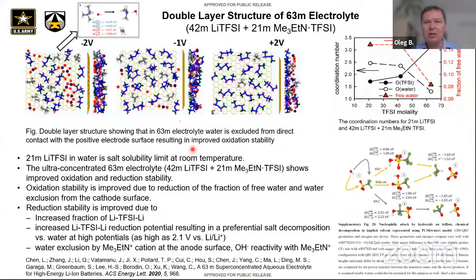One of the ways, Chunsheng Wang's group again came with a new mechanism. They said that, well, we can increase salt concentration further, decrease the amount of water overall, and increase solubility. After they put in trimethylethylammonium TFSI 21 molar salt, they could increase solubility of lithium TFSI to 42 molar. What it does is change the lithium solvation shell from having a little bit more water than TFSI, at 21 molar, to, once going to 63 molar, 3 TFSIs and about 1 water per TFSI.